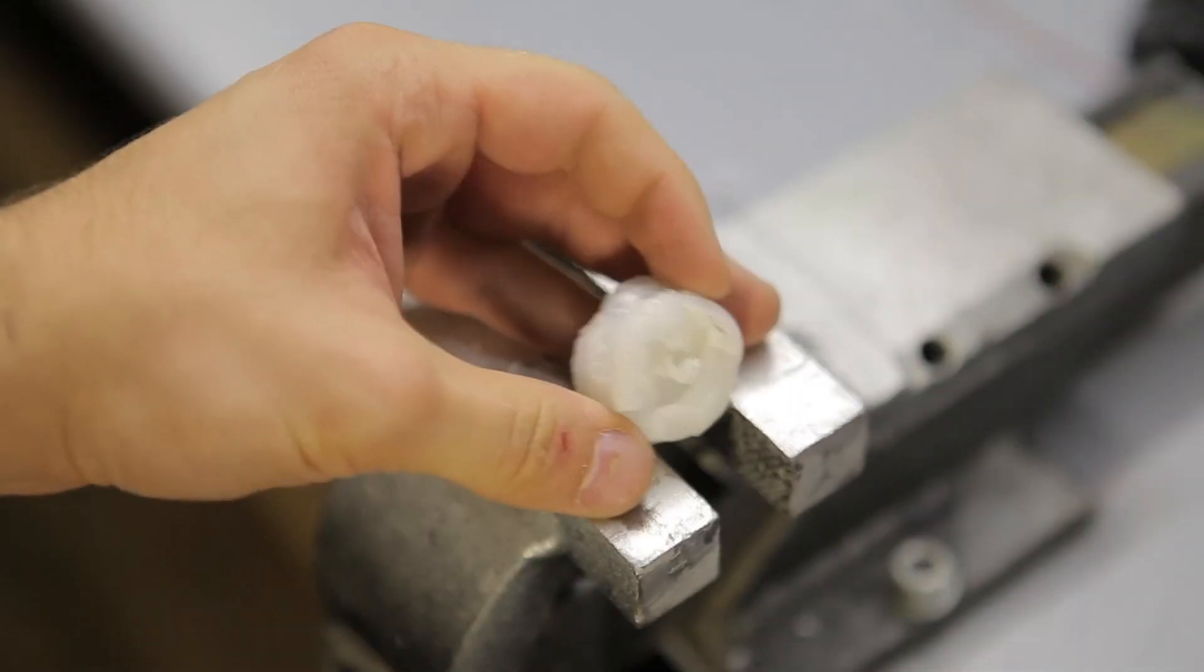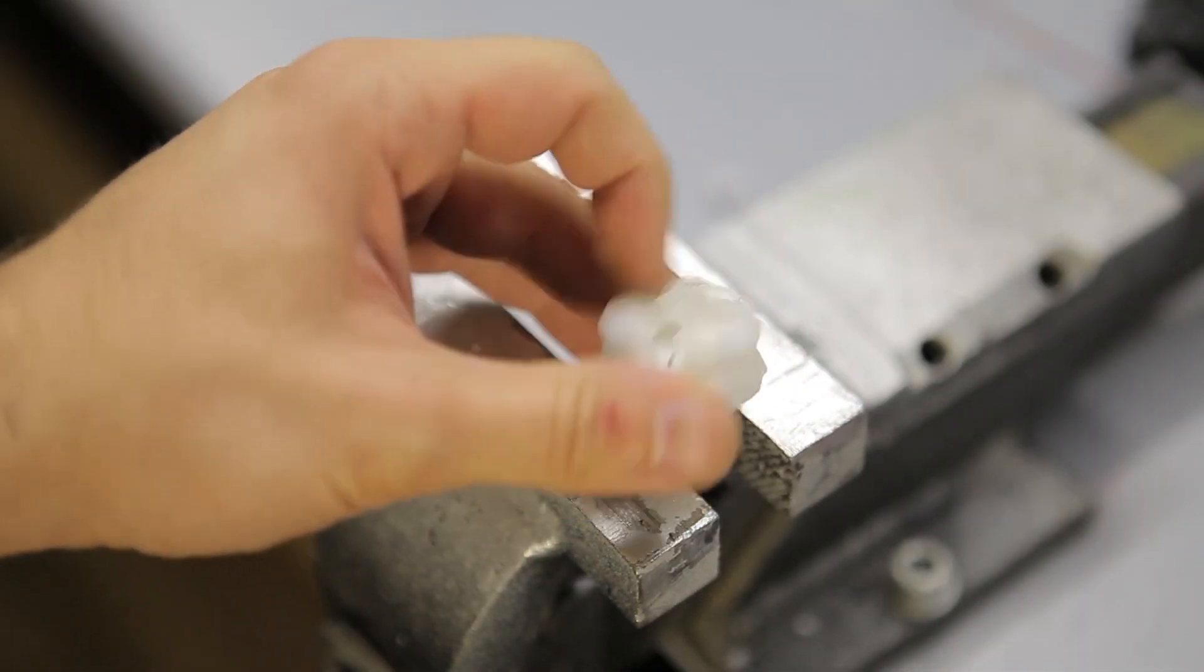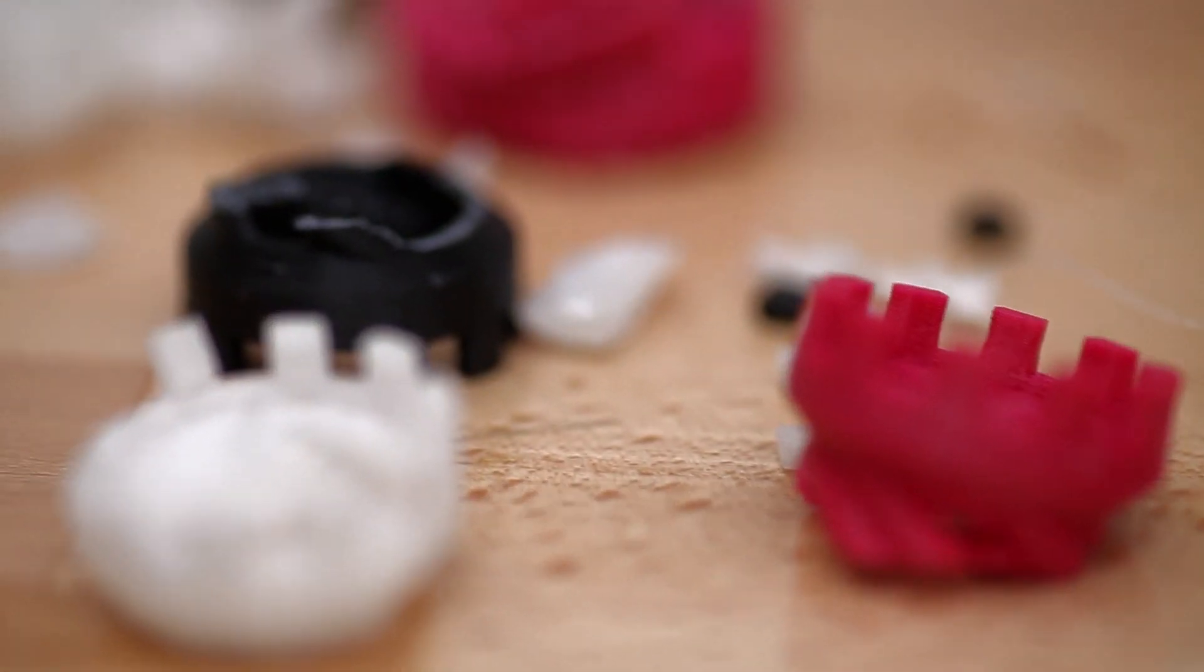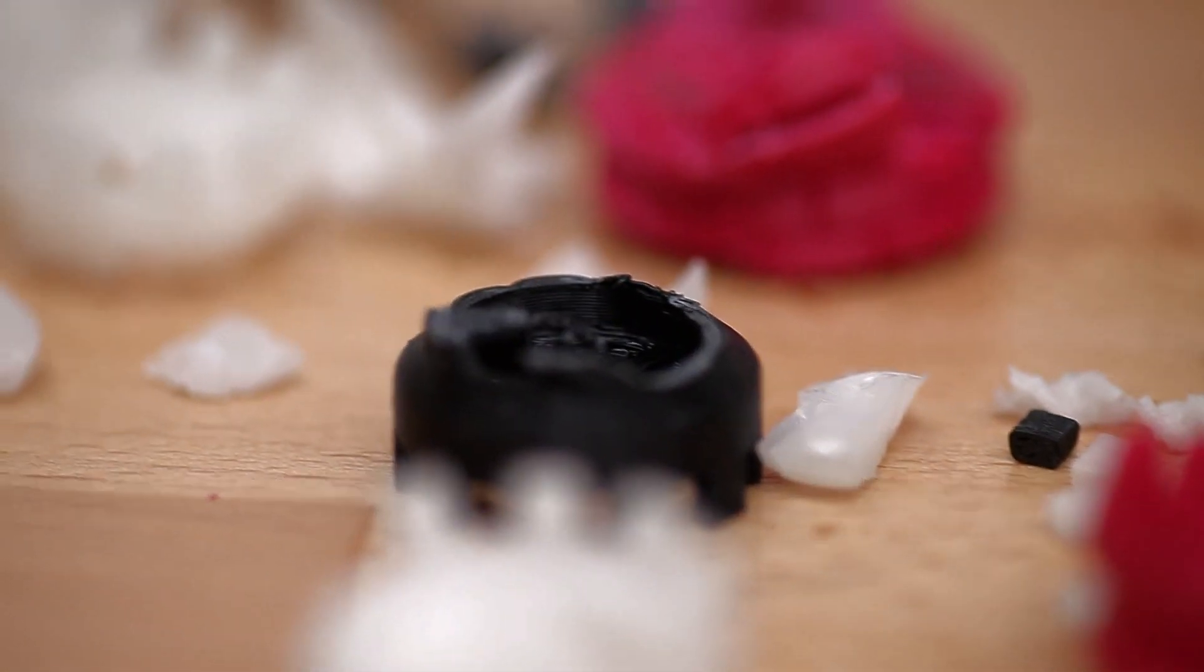And last but not least, the Nylon part, and again, that thing impressed me, it didn't really delaminate at all, it permanently deformed, but this is actually the best performance of them.